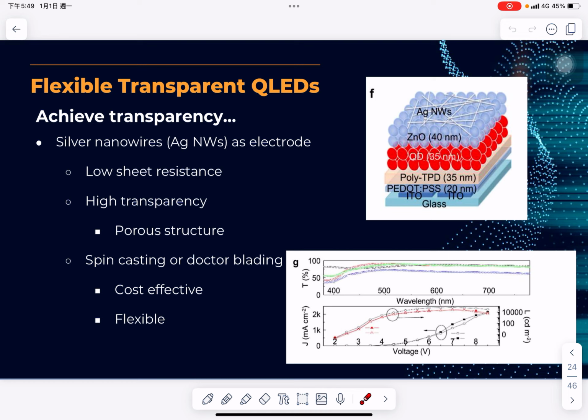Silver nanowires present a transparent electrode option, maintaining low sheet resistance and high transparency due to their porous structure. Applying silver nanowires onto surfaces using methods like spin casting or doctor blading ensures cost effectiveness and extreme flexibility in silver nanowire-based QLEDs.